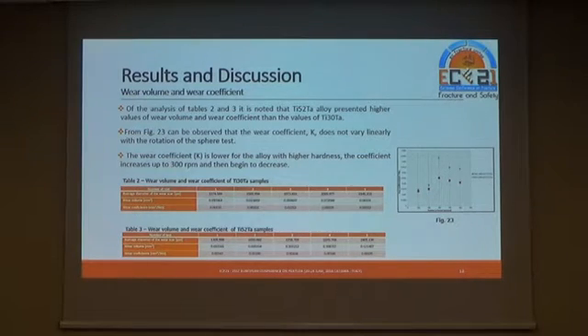From the analysis of tables 2 and 3, it is noted that the Ti52Ta alloy presents higher values of wear volume and wear coefficient than the values of Ti30Ta. From figure 23 it can be observed that the wear coefficient does not vary linearly with the rotation of the sphere test. The wear coefficient is lower for the alloy with the higher hardness. The coefficient increases up to 300 rotations per minute and then begins to decrease.